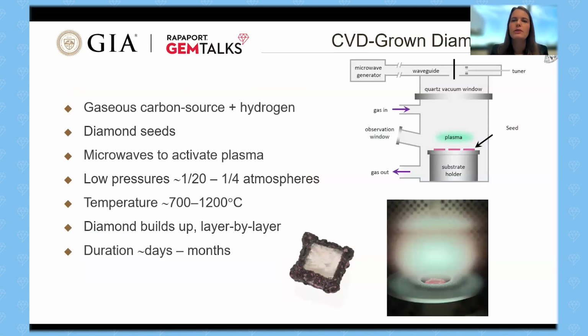Meanwhile, the CVD grown diamonds, the chemical vapor deposition grown diamonds, use a gaseous carbon source and plenty of hydrogen. And you can see here on the right, you have an example of a cartoon of a CVD reactor. You have a series of seeds, again, pieces of diamond that you have to use for growth. And then above that, you have a plasma. You apply microwaves to activate a plasma from all these different gaseous constituents, and then atom by atom, layer by layer, you'll be able to grow new diamond material.